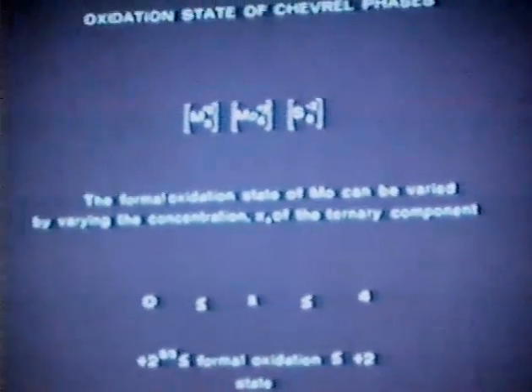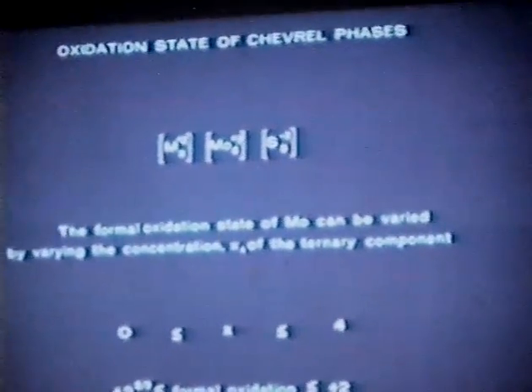If you look at the XPS data, which I'll show you a little bit later on, you can also clearly see that these oxidation states are lower than what you would have for conventional hydrodesulfurization catalysts. And as Russ has pointed out, this gives us a way of really getting into these reduced molybdenum oxidation states that many people have correlated with catalytic activity for hydrodesulfurization.